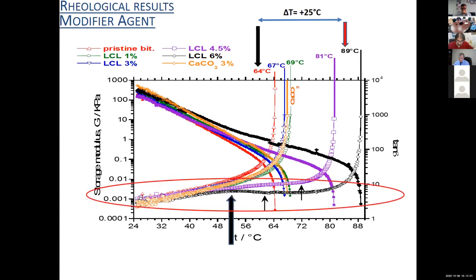It's very important, we observe a sort of a buffering effect. This is a typical phenomenon of the modified bitumen with the polymer, the elastomeric polymer. For this reason, this result is excellent because the rheological behavior of the modified bitumen with the new additives is very similar to the rheological behavior of the modified bitumen with the polymer.